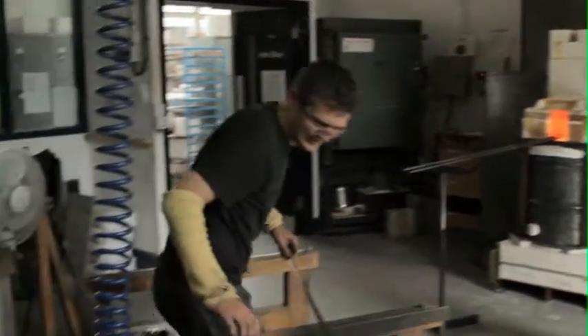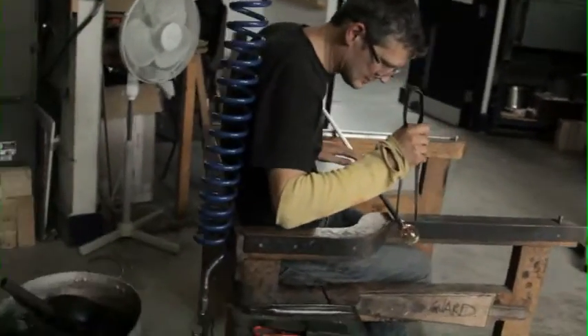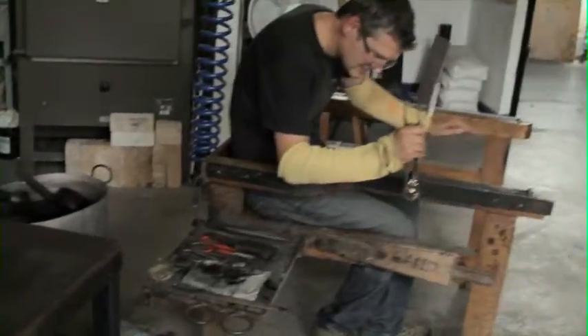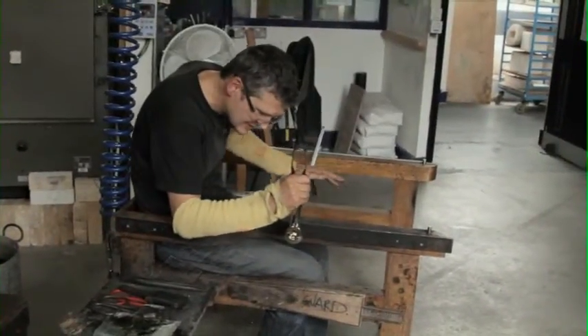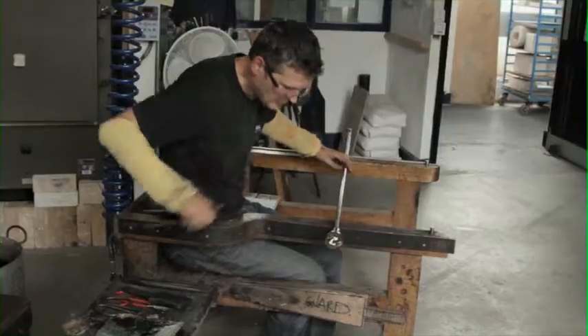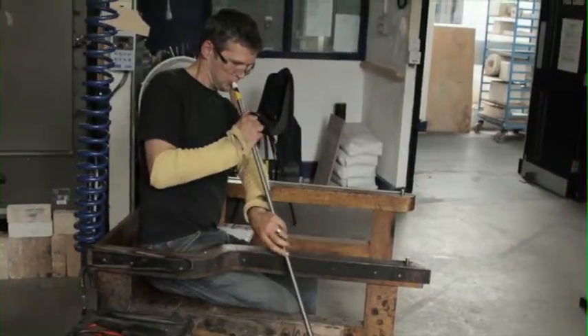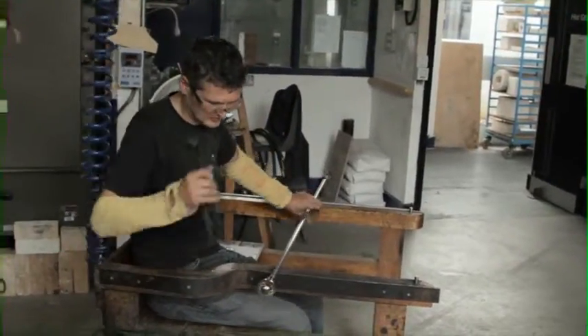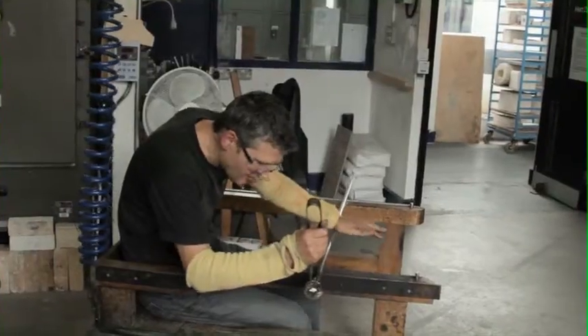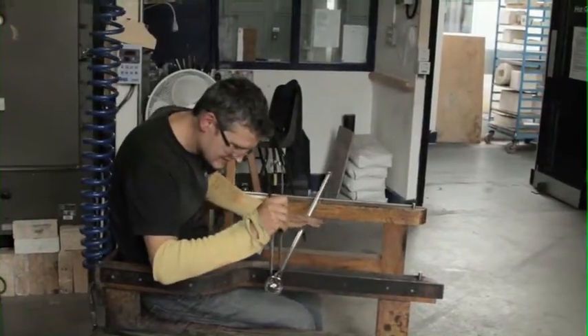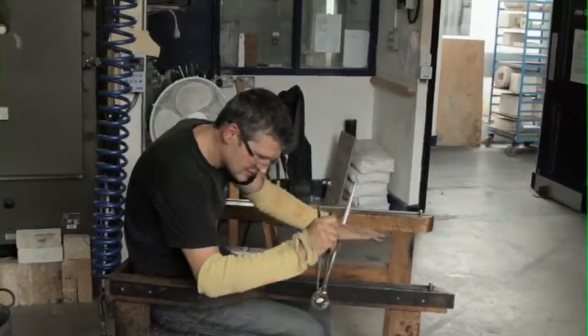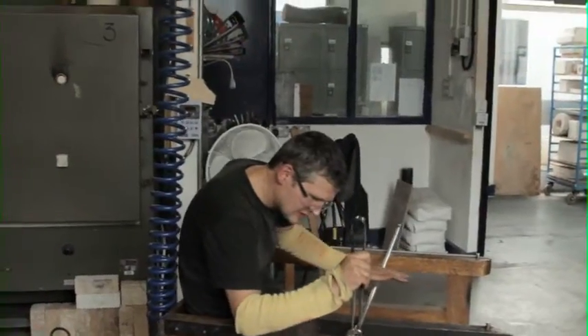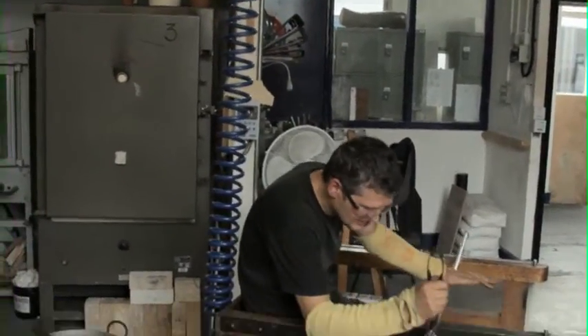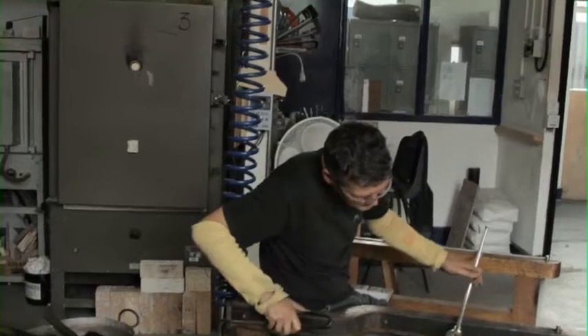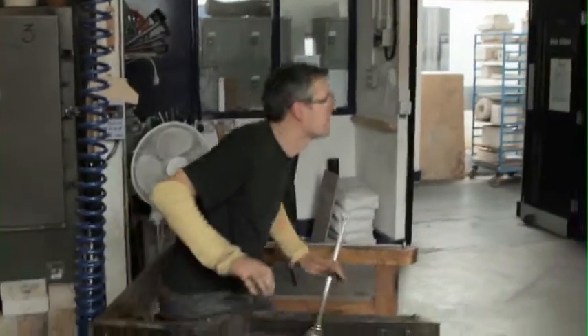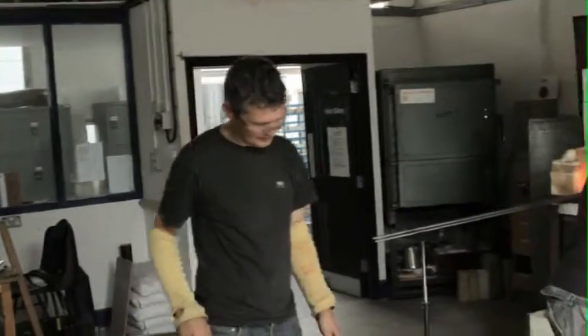Towards the end of the day, when we made enough plates, we made a few objects to see how the glass reacted. I was amazed to find that as well as being long working, it seemed almost impervious to thermal shock. It just didn't seem to want to break, even when it got ridiculously cold and was then plunged into almost 1200 degrees C in the glory hole. It has all the benefits of each of the glass compositions I described earlier, with none of the negative characteristics, discounting the fact that it's so unstable, of course.